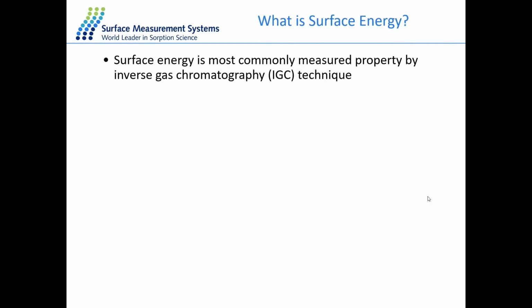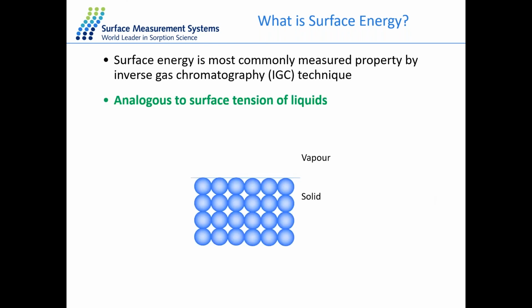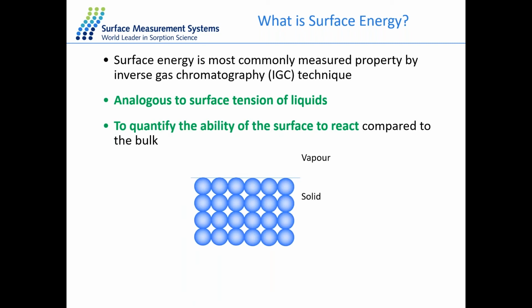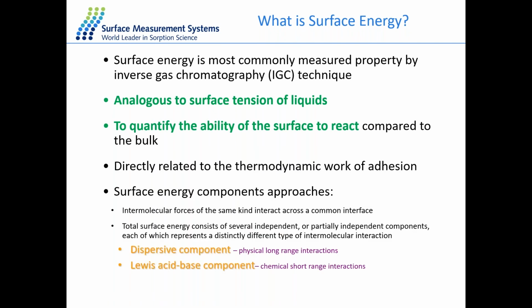So the most common thing to measure using the iGC-SEA is surface energy. Surface energy is analogous to the surface tension of a liquid, and we can understand how the surface reacts compared to the bulk. For this, we need two types of probes. We need to understand the dispersive component. This is in the form of using some n-alkanes, and this gives rise to physical long-range interactions. We also have to inject some Lewis acid-base components, and these are in the form of your acid-base probes. And this gives rise to chemical short-range interactions.